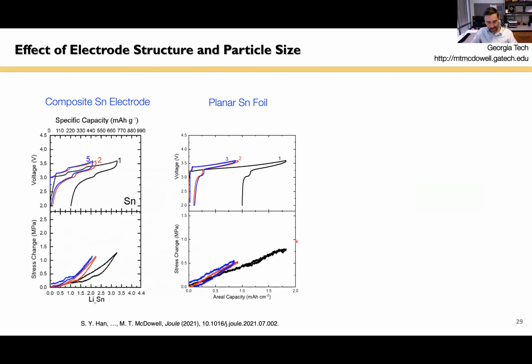And so a little bit more detail now. What we can learn from this with these composite electrodes, you find some interesting things. So first of all, if you compare this composite tin electrode to a planar electrode, so a tin foil that's just a flat interface, two different cells, you see that in the composite structure, you have a large hysteresis in the stress. So we're charging and the stress is increasing here, and then we're discharging, the stress is decreasing, but it does not occur on the same pathway, and there's a hysteresis. And with the planar foil, you don't see this hysteresis, or at least in some cycles, it's a lot smaller. And we think this is because the composite structure has extra void space and other features that can accommodate some of the volume expansion of the particles, which causes this stress hysteresis. So basically, the evolution of stack pressure is affected by the structure of the electrode.